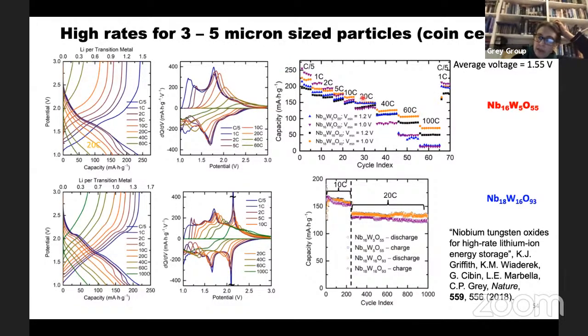So just to explain these notations to you, 1C is the battery notation for taking a battery and charging in 1 hour. So C/5 is 5 hours, and 60C is a 1-minute charge. So what we're showing is that even at 1-minute charge, you're getting reasonable capacity. It's not perfect because it's not engineered, and actually it's the lithium metal that's causing us a problem. But you can see at 20C, we're getting quite a respectable capacity.